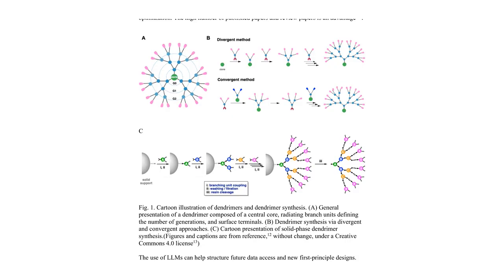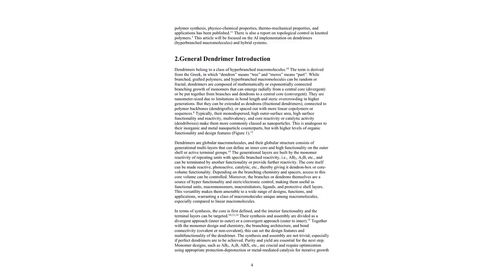In a divergent approach, the structure grows radially outwards from a central core. In a convergent approach, the branches, or dendrons, are synthesized first and then attached to a central core. This precise generational growth gives them a globular, nanometer-sized structure. They are often classified by their generation number, G1, G2, G3, and so on, which indicates how many layers of branching units radiate from the core.